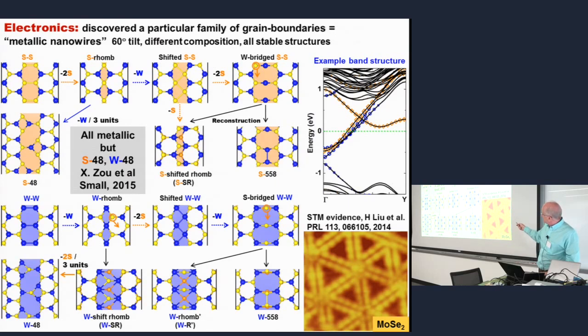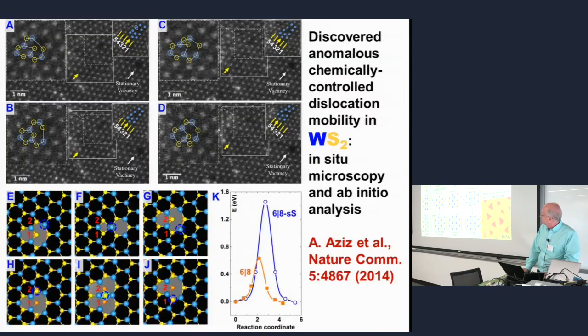But for theory, I just tell you that, yes, analysis shows that they're pretty robust. You see this Fermi level, you see band crossing, so it's pretty robust metallic structures. They're not prone to Peierls instability or any tricks because they're fixed by surrounding lattice. Usually one-dimensional metal is a very finicky thing because it can undergo symmetry breaking and open the gap, but these cannot do it. They can be very mobile.